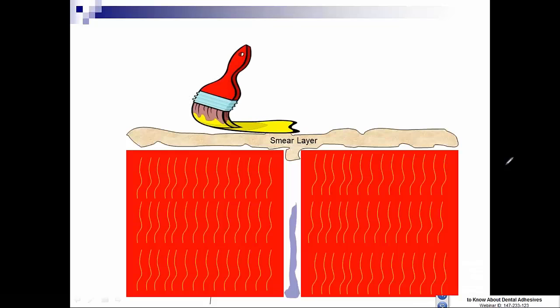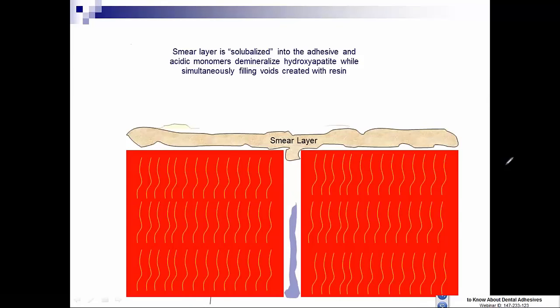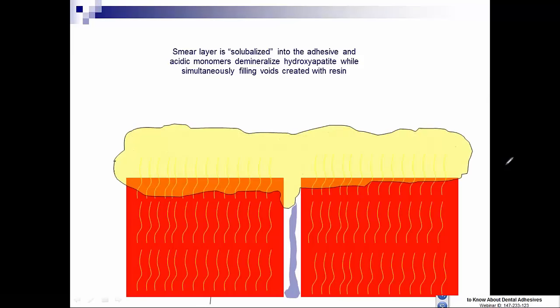So the smear layer, we paint on this self-etching adhesive system, the smear layer is solubilized, and simultaneously fills the voids, the holes created by demineralization. We then air dry that and light cure it. Now, one of the challenges of working with these systems is we have to realize, number one, whatever's in the cavity, and if you recall, I said that sometimes the bits of carbide burr remain in the cavity, becomes part of the adhesive interface.